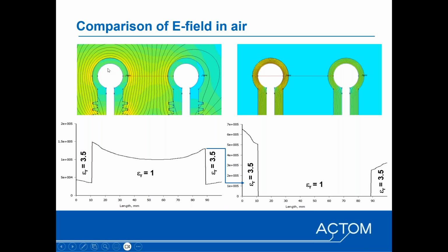Looking at the two scenarios just from a field plot and the field in the air, as I mentioned before, your high permittivity material tends to shift the field into the low permittivity material. So in this case, we do not have an earth screen. The field stress inside the epoxy is low, but the field inside the air is high. Compared to where you've got an earth screen, the field inside the epoxy might be 3 times higher, but in the air there's no field, or the air is not being stressed.